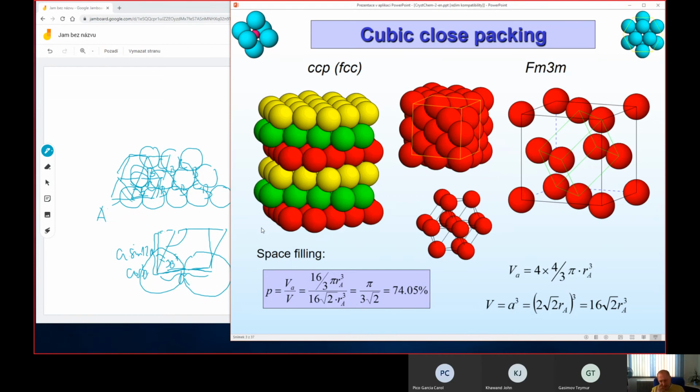But now the symmetry of this arrangement is changed because we can define the unit cell for this arrangement as a cubic one, which from the first glance is quite strange, but the point is that the body diagonal of the cubic unit cell corresponds to the direction of sequencing the layers along the C parameter of the original hexagonal lattice.